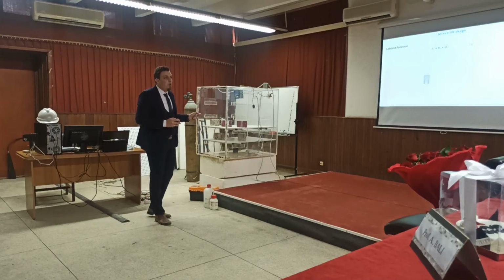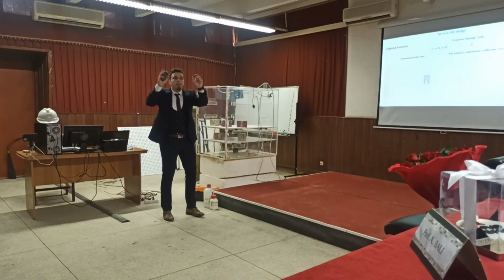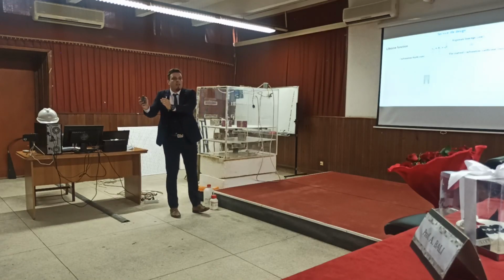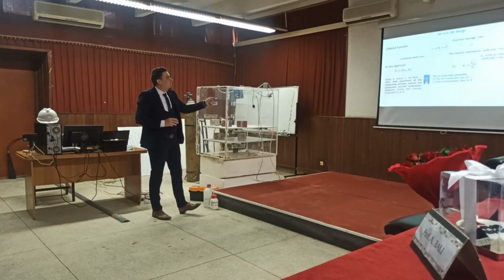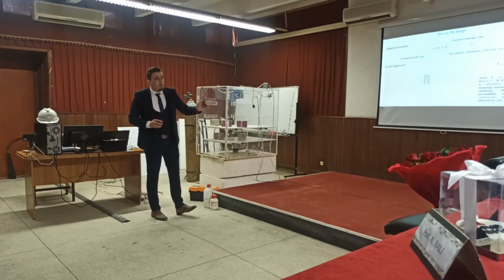Now, in order to develop our lifetime function, we start with Fick's first law. This is for natural conditions of carbonation. I told you that we already have a relationship between permeability and accelerated carbonation. In order to use this, we need to make the conversion from accelerated to natural. In this case, we use the relationship developed by Neves in 2013. This is the formula to make the conversion from accelerated to natural. And for the relationship between accelerated carbonation and permeability, we use the relationship also developed by Neves in 2015.